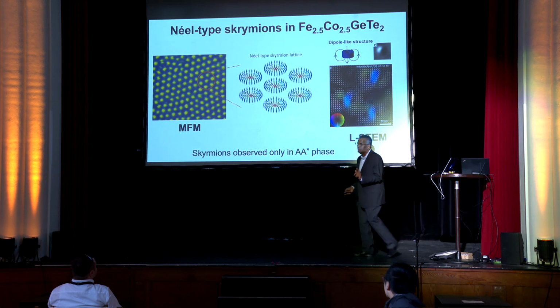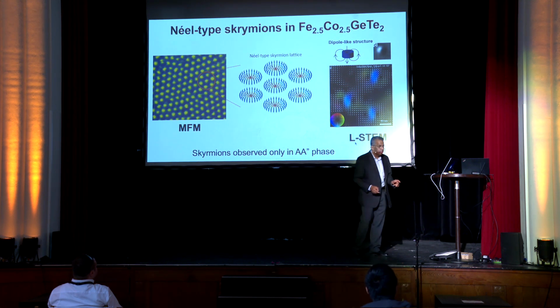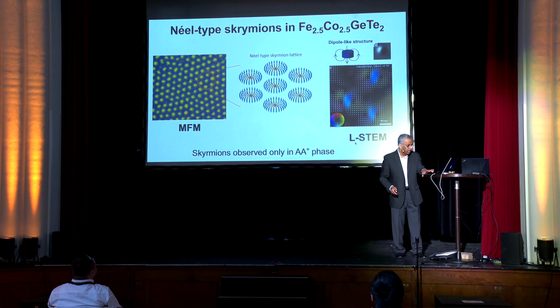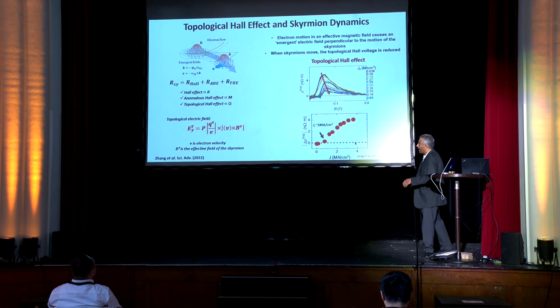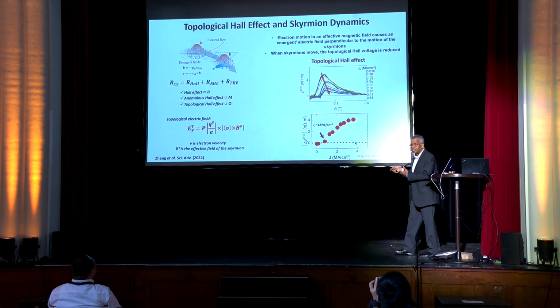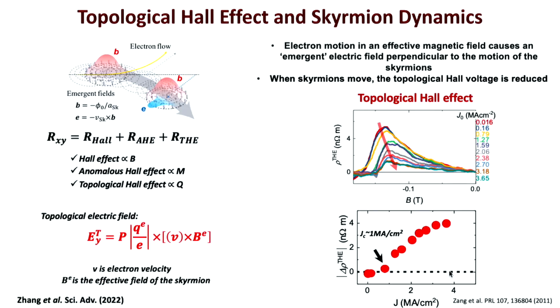So the broken inversion symmetry is incredibly important for the formation of these magnetic textures. And accompanying that, you could also see the topological Hall effect. This was a very difficult experiment. It took us a while to get this done. And this just tells you the various contributions to the measurement: the resistances, the Hall, the anomalous Hall effect, and the topological Hall effect. And that is because of this topological electric field that you create.